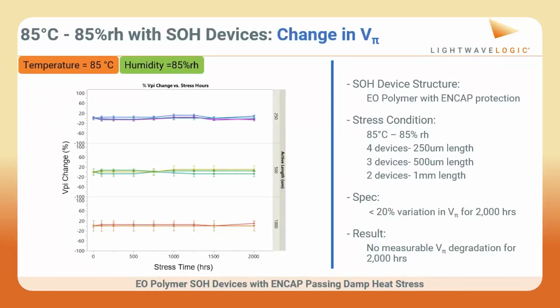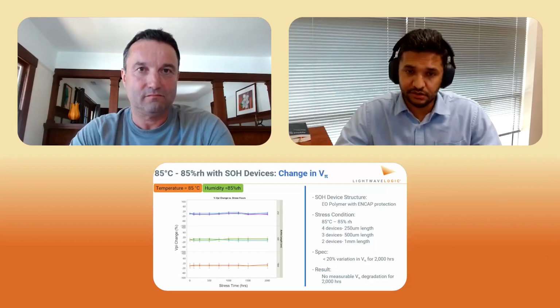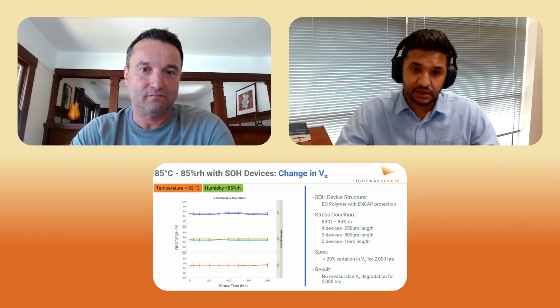Yeah. I mean, this was our biggest breakthrough in reliability yet. What we did is we took our fully encapsulated silicon organic hybrid devices, and we put them in what is called 85/85. And what it means is we put it in an oven which is heated to 85 degrees Celsius and 85% relative humidity. So it's a very harsh condition that we put our devices through, and we monitored their VPI for 2,000 hours.